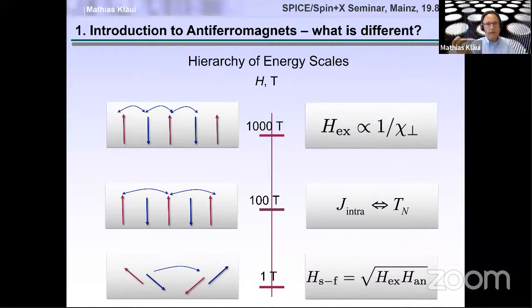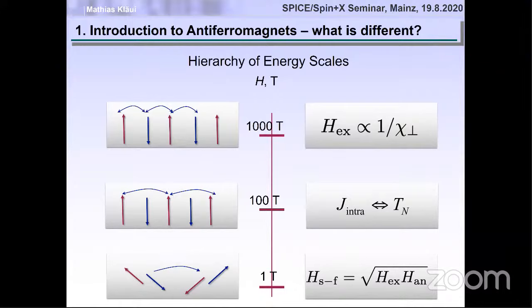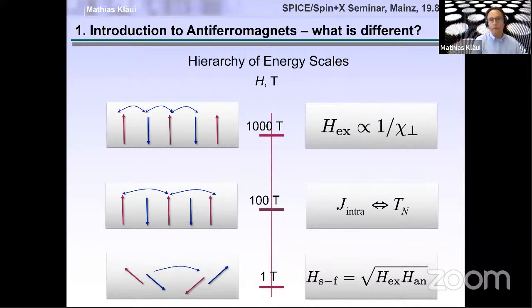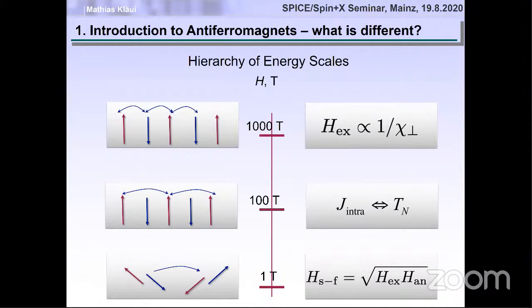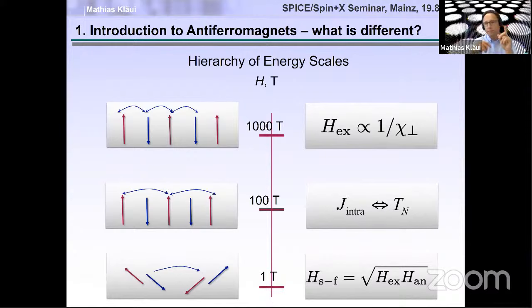Yes, the microscopic interactions that drive these phenomena. If you look at what drives these phenomena, the antiferromagnetic inter-sublattice exchange drives this. The intra-sublattice exchange gives the Néel temperature, and the anisotropy drives the spin flop together with the exchange field. Now, the type of anisotropy that you have depends very much on the system. In nickel oxide, we have an easy-plane system. In hematite, we have an easy axis below the Morin transition.